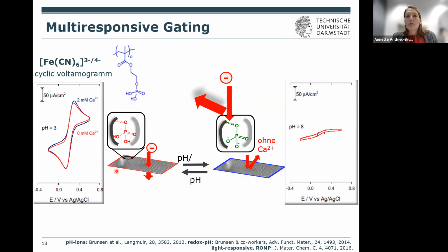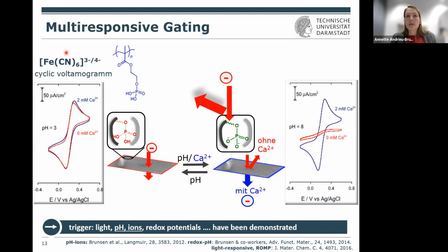So when we did this in 2012, this specific example was known, and we were interested in what actually happens if you add calcium. And the intuitive hypothesis was that calcium, if you're a chemist, you know this, complexes phosphor groups. So you have two valent electrostatic interactions, and then the pore should get neutral. And this is actually what you see if you add calcium in low amounts. The pore opens again for the negatively charged probe molecule. So right now, I think this concept for a certain amount of polymer is demonstrated for almost every stimulus you can imagine. I recently read a paper, I think 2 years ago, that even magnetic stimuli have been investigated. So ions, pH, light, redox potentials. This works fairly well. So this opening and closing electrostatically by using responsive polymers.